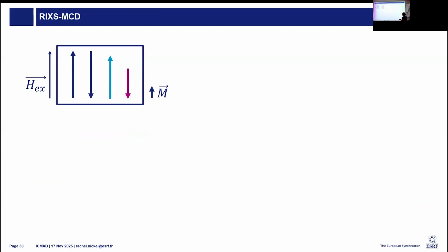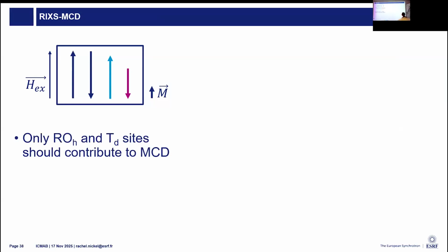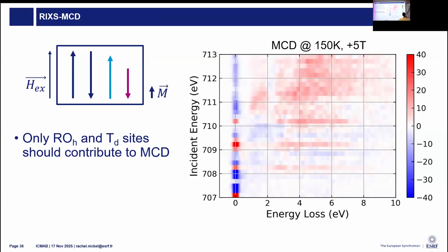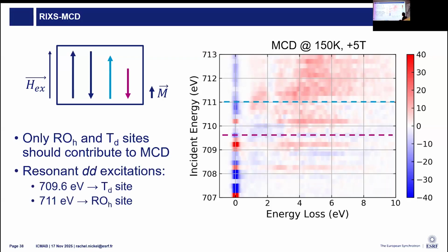So we turn to RIXS MCD. These measurements were taken on the small spectrometer, so it's attached to the magnetic field. We know from the magnetic structure that only 2 sites should be contributing. And when we look at the RIXS MCD map, sure enough, we see that there's 1 site in red and 1 site in blue. And this reflects the anti-parallel coupling of spins. From the resonant DD excitations at 709.6, we attribute it to the tetrahedral site, and 711 eV to the regular octahedral site. This is consistent with what you would get with simulations where we have a sensitivity to the bond length, causing a shift in the white line of the individual XAS spectra.